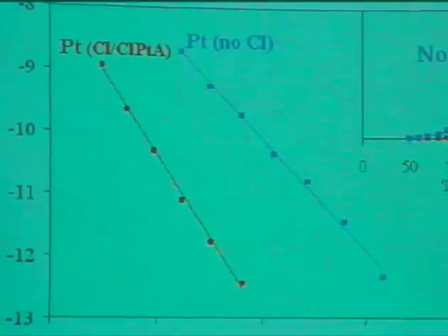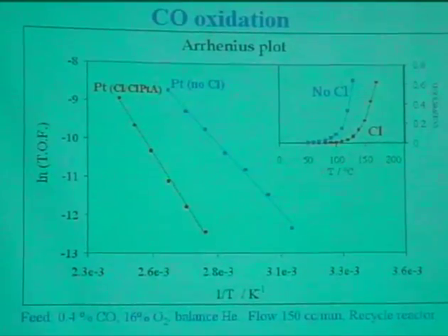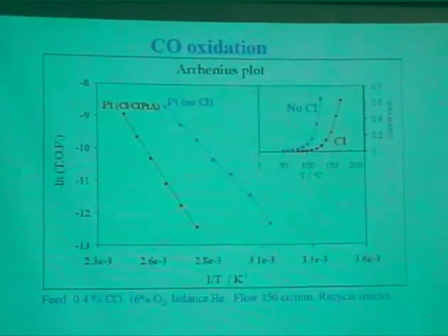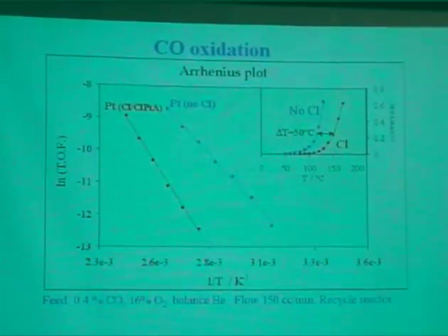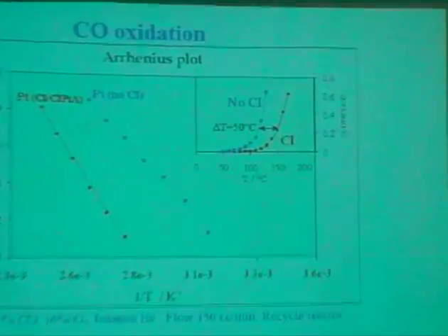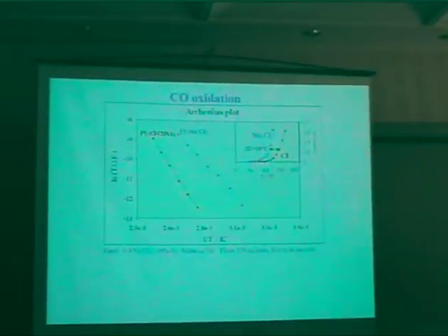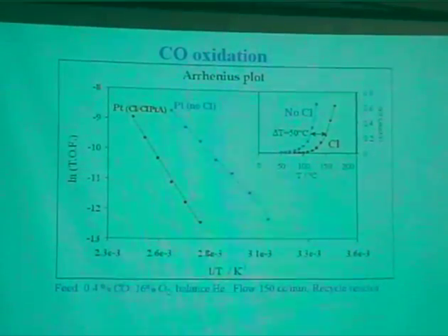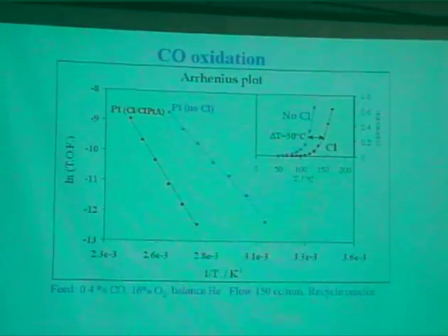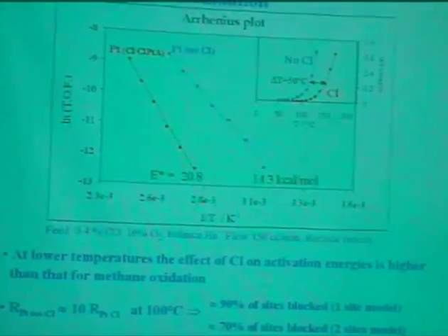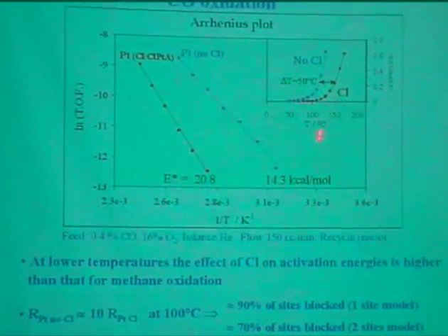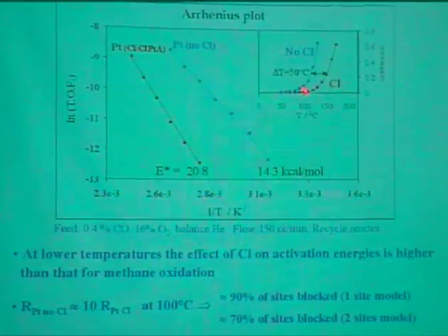Well, we started with methane, and we thought, well, CO oxidation had to be somewhere there, and so we repeated the results with CO oxidation pretty much under similar reactant concentrations and flow rates. And again, we observed that the chlorine-containing catalysts have significant differences. The temperature change here is about a 50-degree difference. Have in mind that the rates double every 10 degrees at temperatures around 150. So this is not as large as in the case of the methane reaction, but still it's an order of magnitude difference in the rate at 100 degrees centigrade. So very little reaction there compared to this.